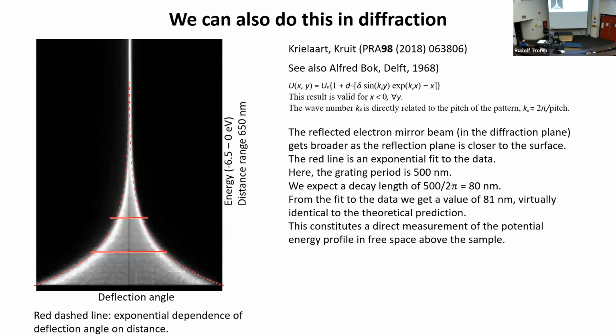You can also do this in diffraction. We can look in real space. We can also look in diffraction. The angles are deflected, so in diffraction space, the angular distribution broadens in the direction perpendicular to the grating. Here you see this exponential increase of the width, and we find from that that it should decay with a decay length of 80 nanometers. We measure 81 nanometers. Good, Maxwell's laws work, right?